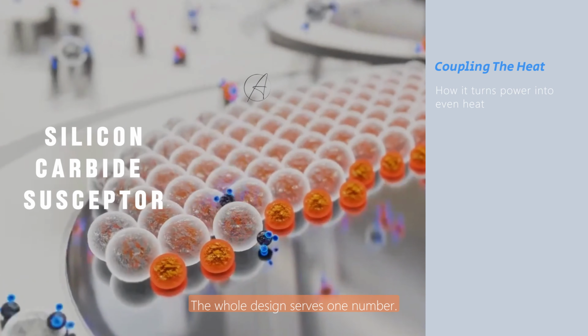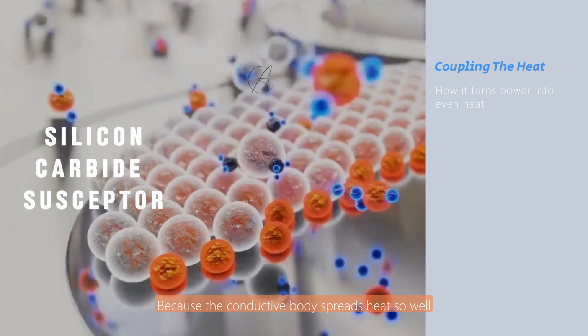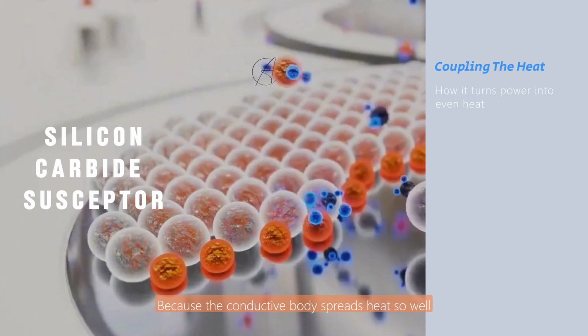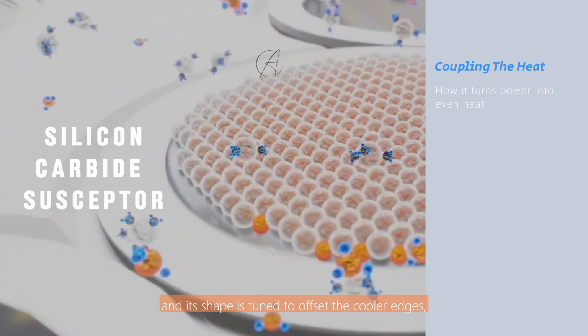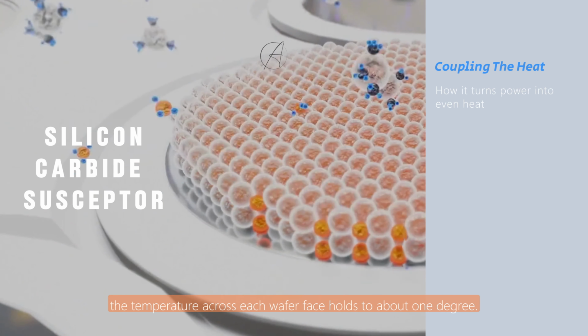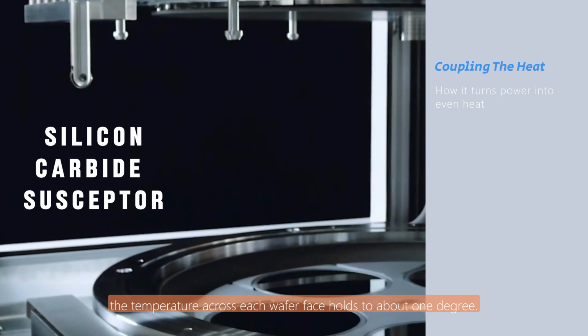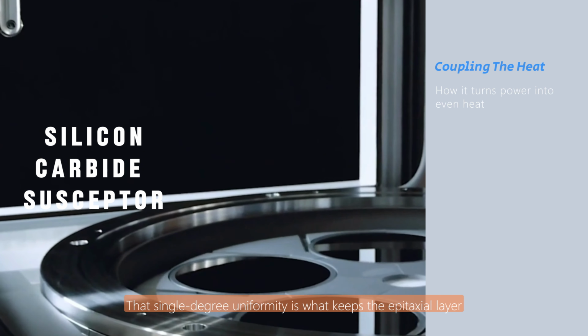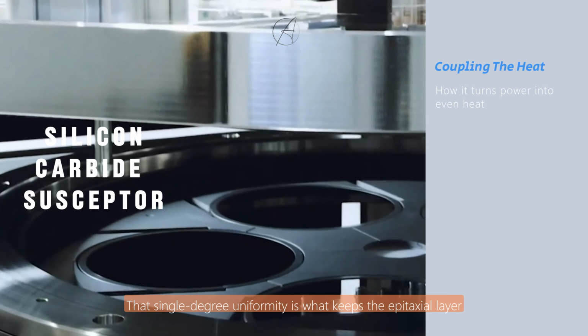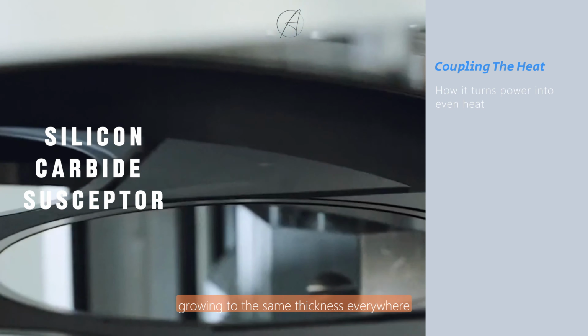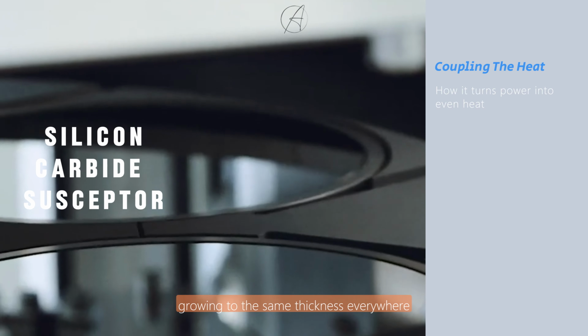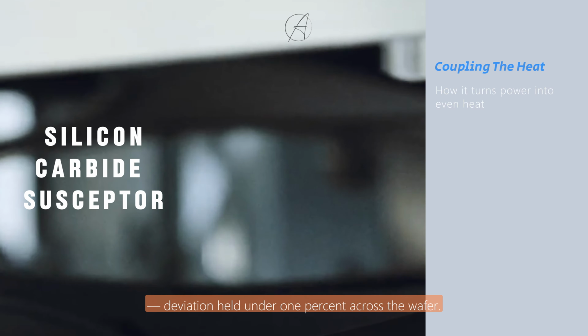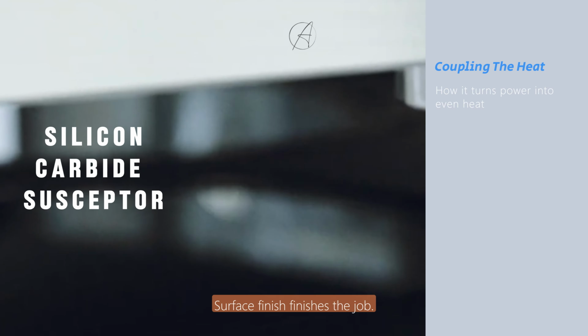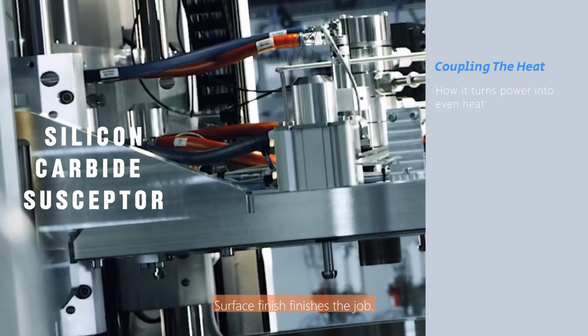The whole design serves one number. Because the conductive body spreads heat so well and its shape is tuned to offset the cooler edges, the temperature across each wafer face holds to about 1 degree. That single-degree uniformity is what keeps the epitaxial layer growing to the same thickness everywhere, deviation held under 1% across the wafer.